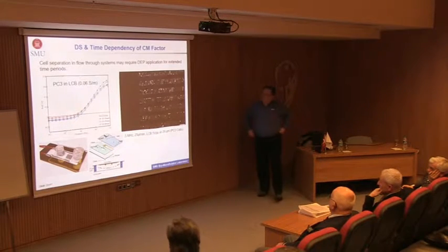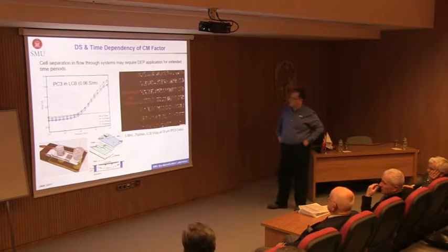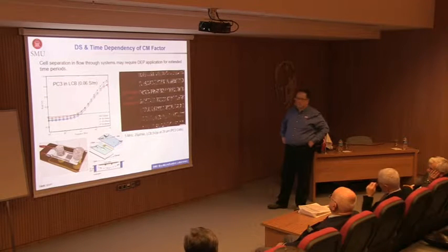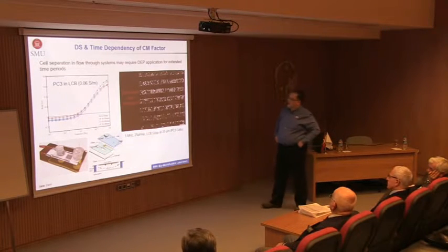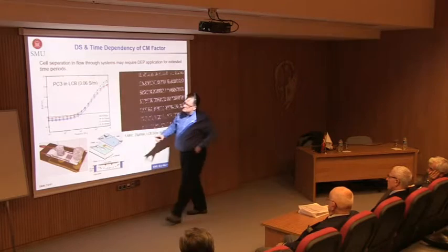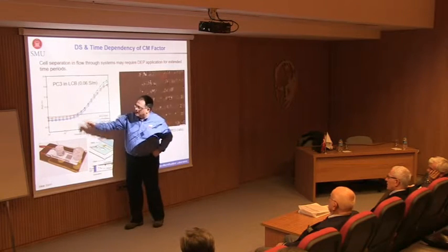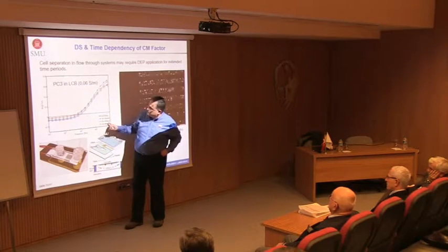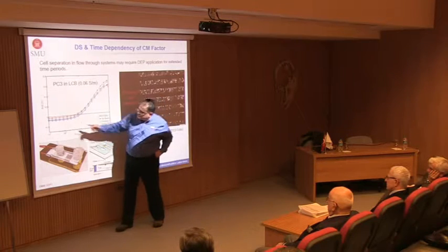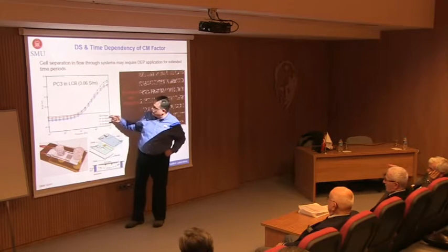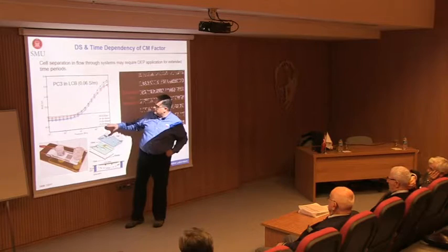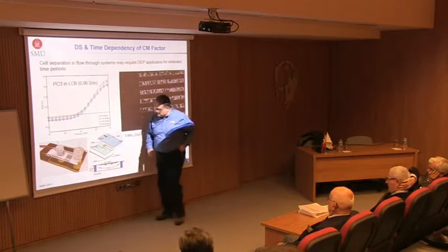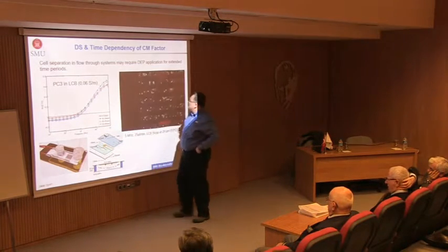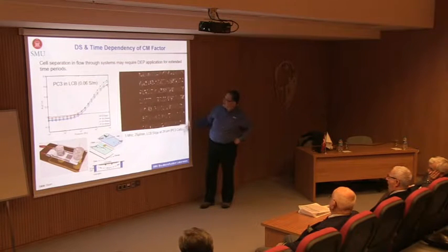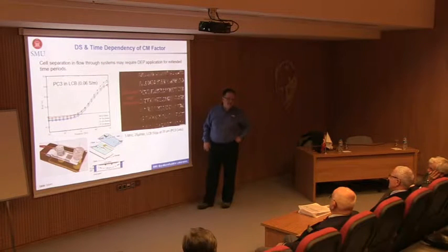Here's an example of what happens when you deal with PC3, that's basically prostate cancer cells. And first of all, prostate cancer cells show very weak dependence on time. These are different dielectric measurements that we did, and the Clausius-Mossotti factor that we obtained up to 10 minutes and up to 40 minutes with different colors in a simple device like this. And as you can see, when we turn on the electric field, we start getting them.